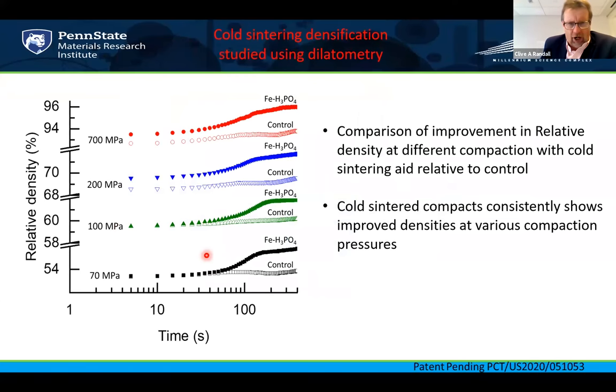So just to give you an idea here, there's a lot of data on here. Here's the relative densification. This is dilatometer data. So the controls mean that there are no special additives besides the commercial process. This is an Fe powder. They're all commercial powders. These are the ones with different coatings, in this case, the phosphate coating. And you can see here that we then get a small but significant cold sintering enhancement. And of course, this is very much controlled by the pressures that you are doing your compaction at.